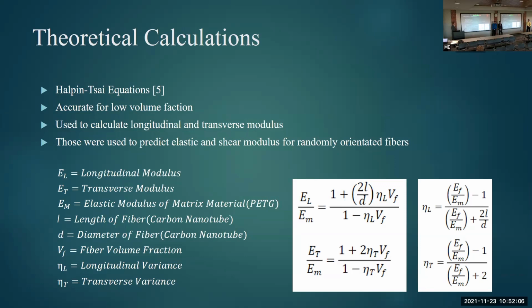So we did some theoretical calculations to figure out what we might see out of mechanical properties from our nanotube composite. The main thing we used was the Halpin-Tsai equations. These are popular equations for figuring out the moduluses of a matrix and fiber composite material. They're accurate for low volume fraction of the fibrous material, which we are planning on using. We're planning on only using between 0.1 to 5% carbon nanotubes in the PETG.